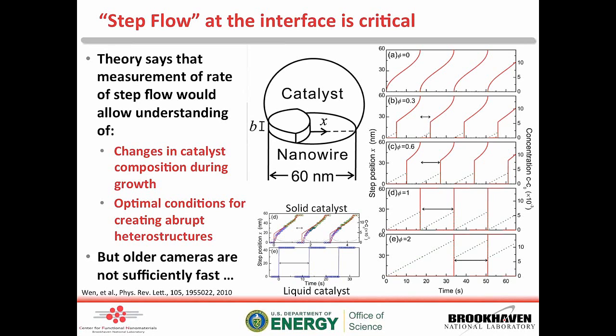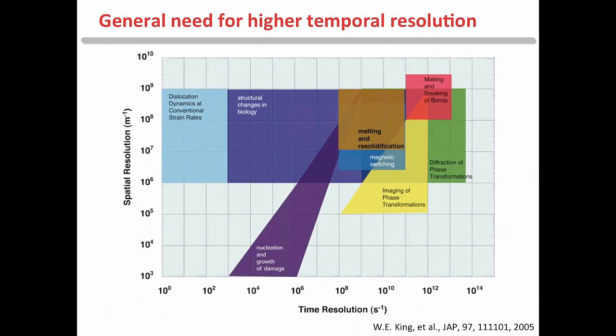And by measuring things like the catalyst, the interfacial step growth rate, you can actually learn quite a bit about this process. So if you look in the upper right, if you have a solid growth, you can have nice slow incorporation of steps, and in liquids it's very fast. And really, with the older cameras, it wasn't fast enough for us to image this. And so this kind of points to the need to go to higher frame rates.